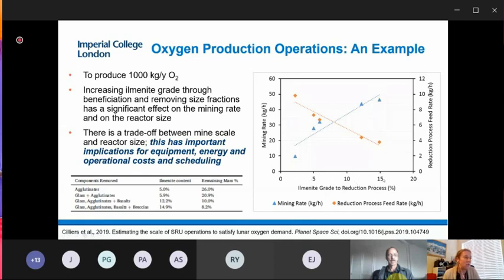Now, those blue triangles are the mining rate. And we can see that as we strip out more and more components, the mining rate increases. So by reducing more and more of the components to increase the ilmenite content, we need to have a bigger mine, effectively. But what that does do, you can see by the orange diamonds, is reduce the size of the reactor. So by adding a beneficiation stage, we need a bigger mine to produce the same amount of oxygen, but the reactor is smaller. And if it's the reactor that requires the energy to heat the regolith to produce the oxygen, then perhaps this would be a better route. And actually, the discussion, the trade-off between bigger mine and small reactor, or small mine and big reactor, is one that hasn't been had so far.